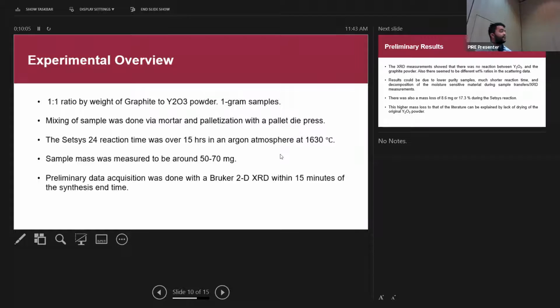The Setsys 24 reaction time was over 15 hours in the argon atmosphere at 1,630. We couldn't extend the time because the instrument has limitations on the time. So in the future, we're planning on using a furnace to extend the time.